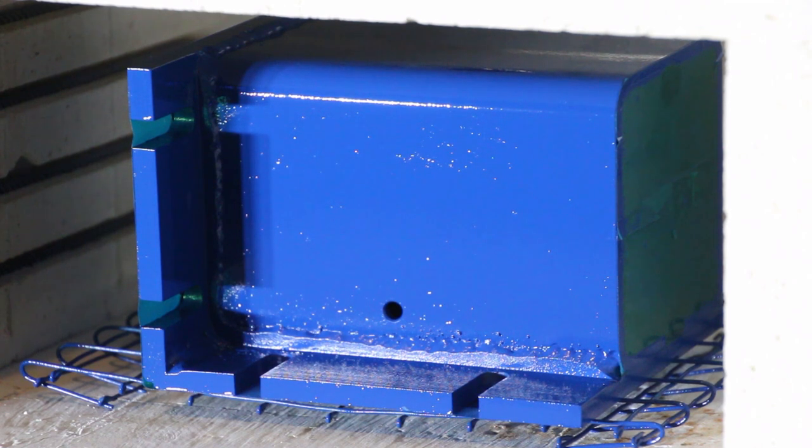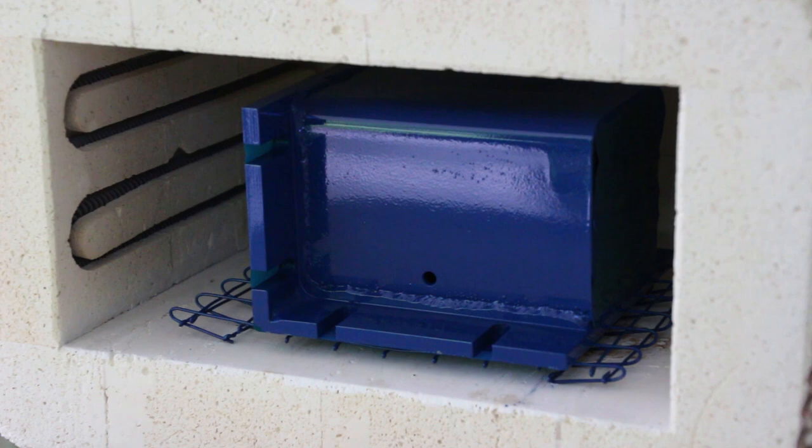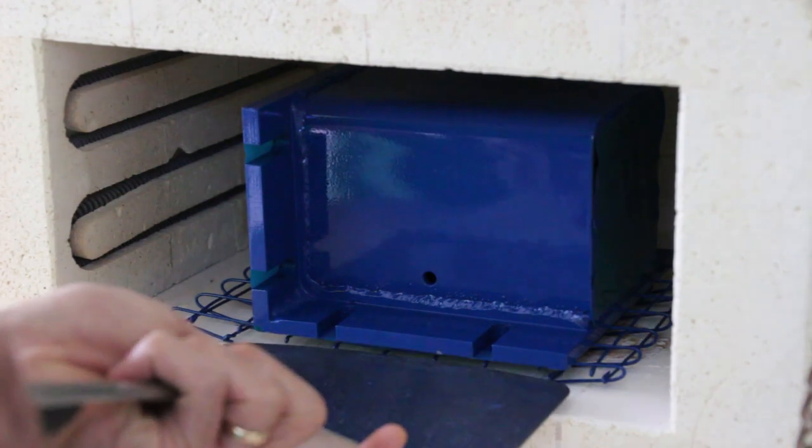So now I'll turn the oven down to 400 degrees Fahrenheit or approximately 200 degrees Celsius. I let it bake for another 20 minutes and then shut it off and let it cool overnight. You don't need to wait that long, but you do want to wait long enough that you're not taking it out while the coating is still liquid.